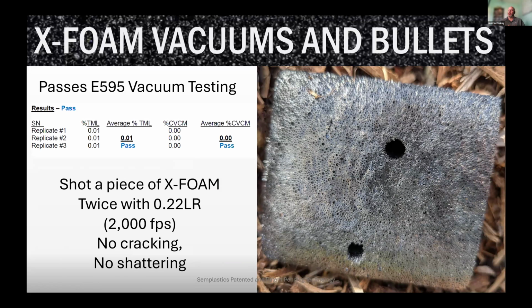And then I wanted to demonstrate somehow that this stuff is not brittle. So I shot it with a .22 LR, and it did not crack. And we're not claiming it can stop bullets. It will stop a nice BB from a Red Ryder BB gun and catch it in less than an inch of material, but it will let things through. But it is very not brittle because it has some toughness to it. It'll bend. The strain of the material is a lot more than a regular ceramic,